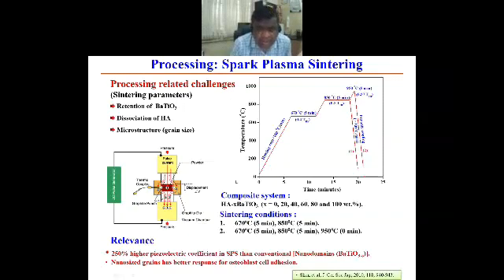So what you see here is barium titanate with the processing approach that we have adopted, the spark plasma sintering approach. In spark plasma sintering, we have used not a single-stage sintering but a multi-stage sintering technique. That means holding the hydroxyapatite barium titanate at 3 different temperatures, 670, 850, and 950 degrees Celsius. We did not hold at 950. We just heated it and then brought it to room temperature. With these kinds of processing approaches, we could address most of the 3 aspects that we have mentioned on the right-hand side.